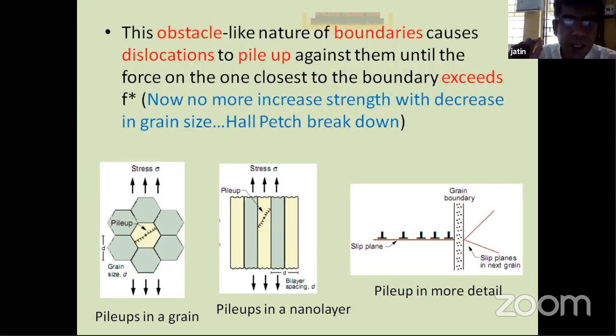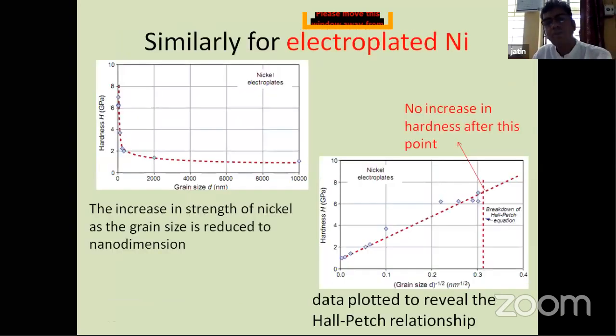The dimensional stability has to come. Your grain has now come to the dimension of the dislocation, and the dislocation is now able to bypass that particular grain. And that is why we observe this type of feature in materials. A similar case is seen with nickel on a normal scale, and when you plot it on a logarithmic scale, the same thing is observed with nickel. So there is a breakdown taking place in the material.